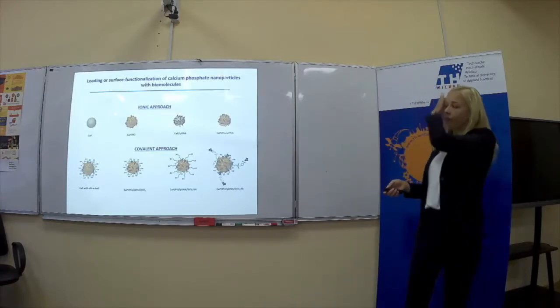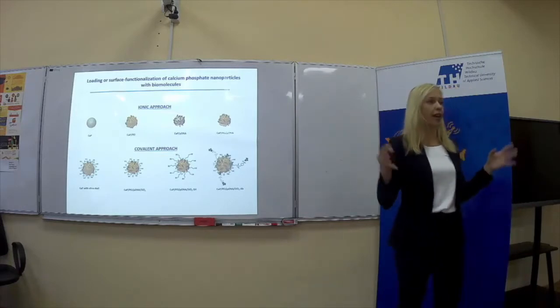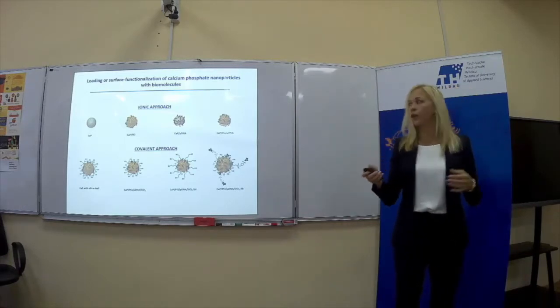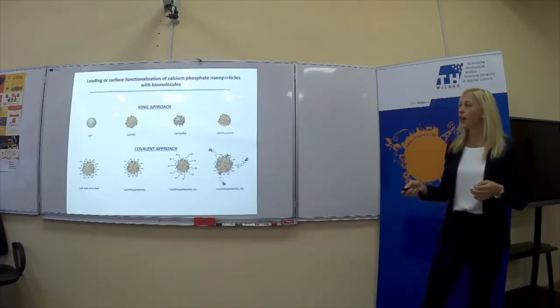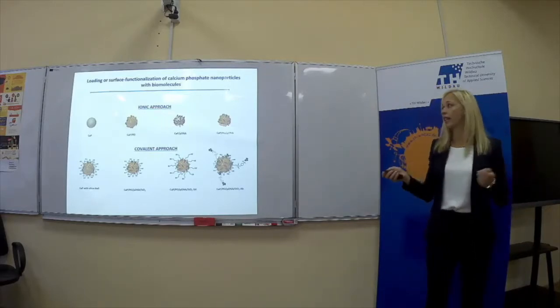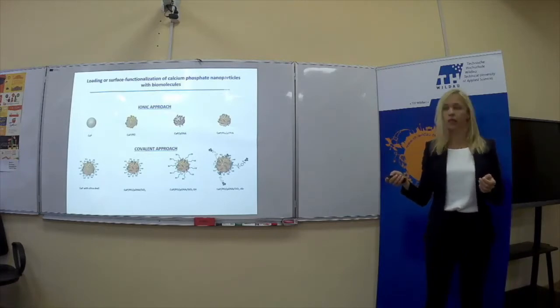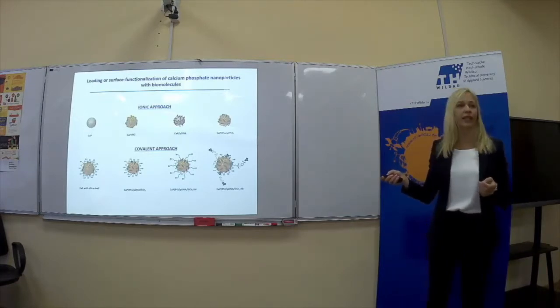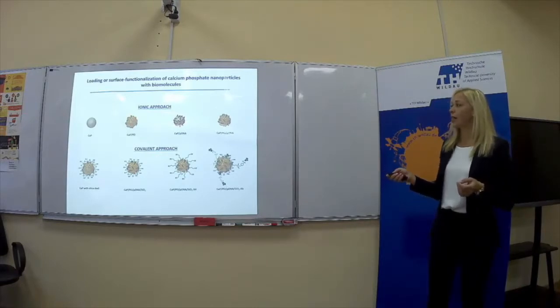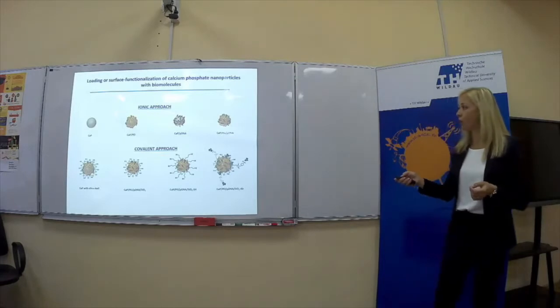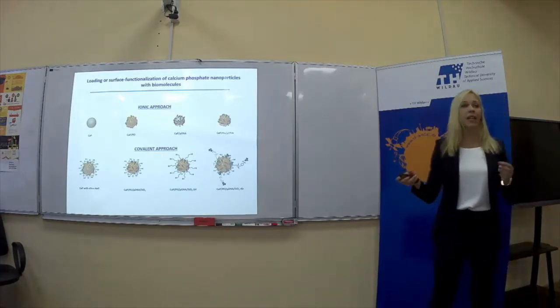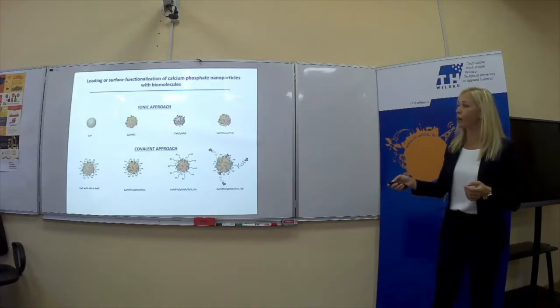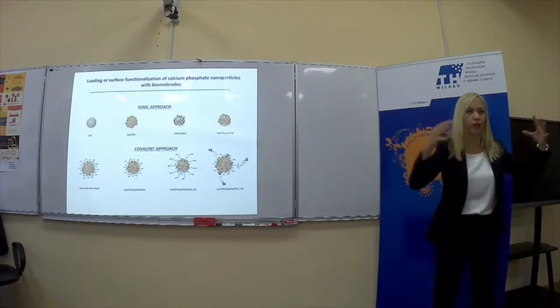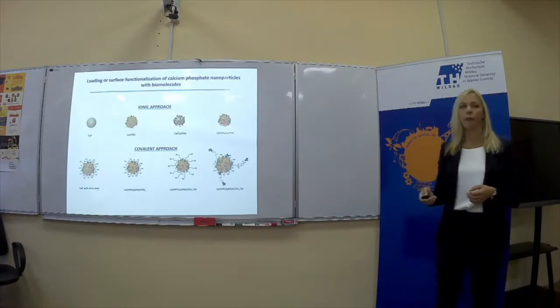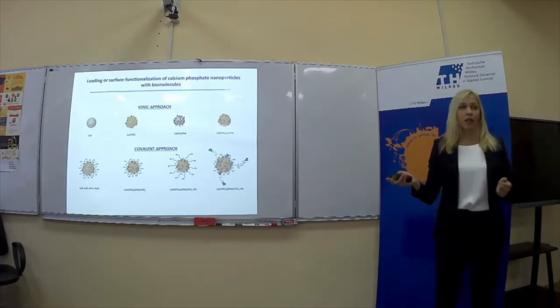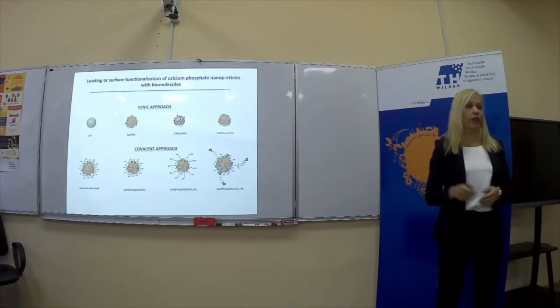Here you can see there are two kinds of approaches for adding biomolecules on the surface. In the first approach, if you have calcium phosphate, you can add, as I told you, different kinds of biomolecules. For example, you add positively charged polyethylenimine, and you have such nanoparticles; you can add DNA, and you have another type of nanoparticles. Or you can mix them: you have calcium phosphate, you add positively charged polyethylenimine, and then you add negatively charged DNA molecules. These are great nanoparticles. I was working with such nanoparticles for a long time.